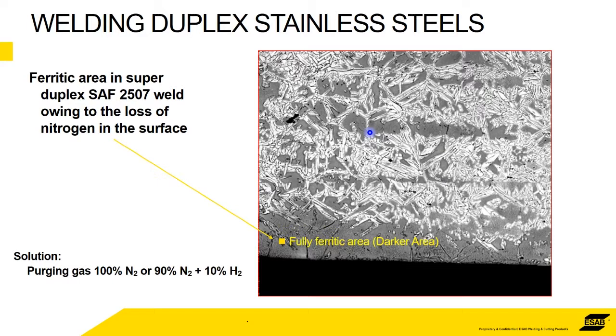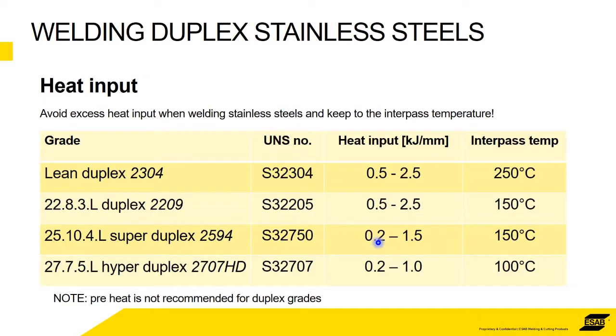In terms of purging gas, basically the same again. We would recommend 100% nitrogen, or certainly 90-10 hydrogen. In the bottom of the weld here, you can see again it's a fully ferritic area, so there's no strength, there's no corrosion resistance in the bottom of the weld. That's why we recommend using nitrogen in there. Okay, nitrogen will convert the ferrite into austenite to give you a good duplex mixture.